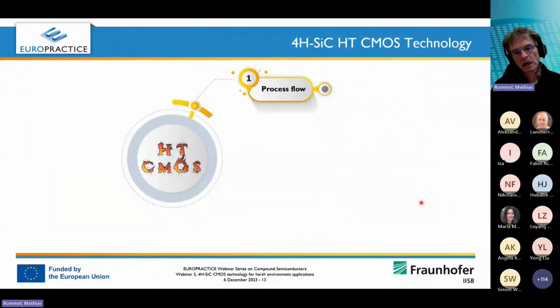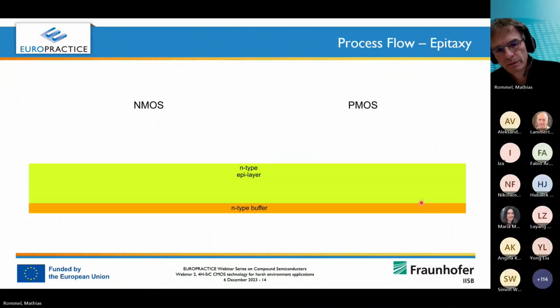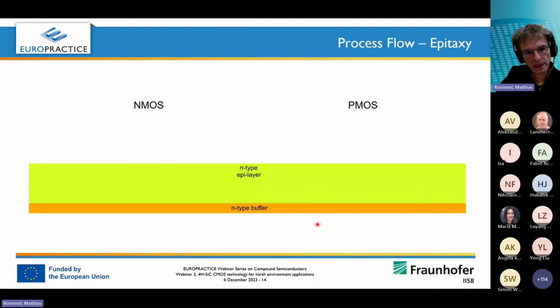Let's start with the process flow, and I will now very briefly go step by step through the main process steps we need, and also talk a few words on why some steps are necessary or not. Let's start with the epitaxy. You might have heard in the last talk that the silicon carbide substrates, which are below this here, where you don't see it, they still don't have the quality which we need to fabricate devices. That's why we need an epitaxial layer, and that's a very standard epi layer. We have an n-type buffer and then an n-type epi layer on top of the substrate.